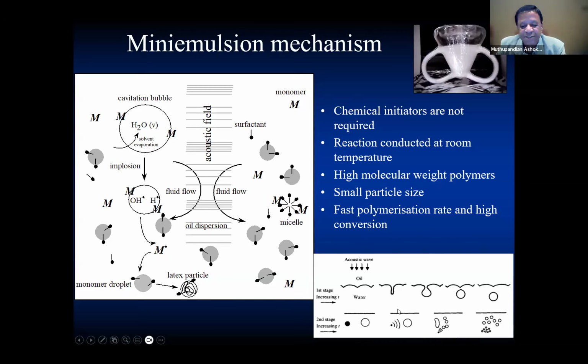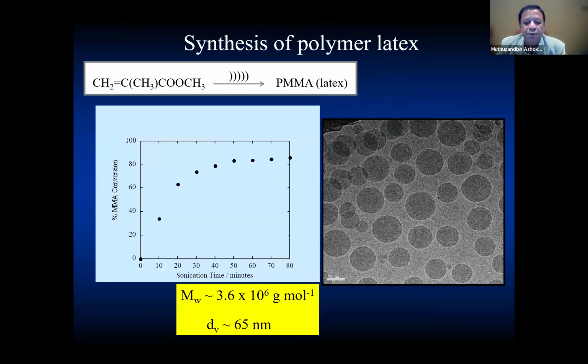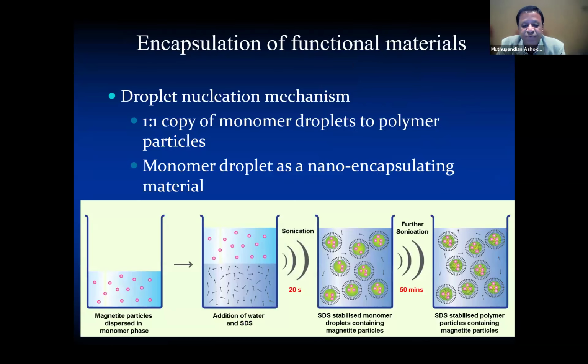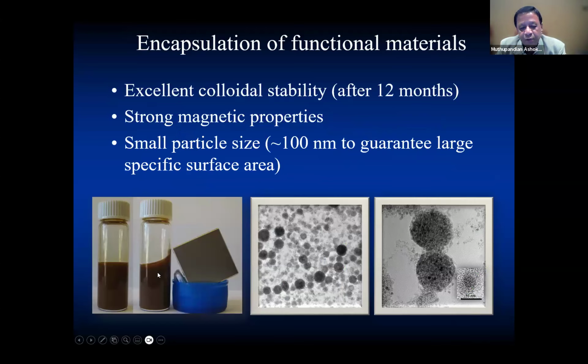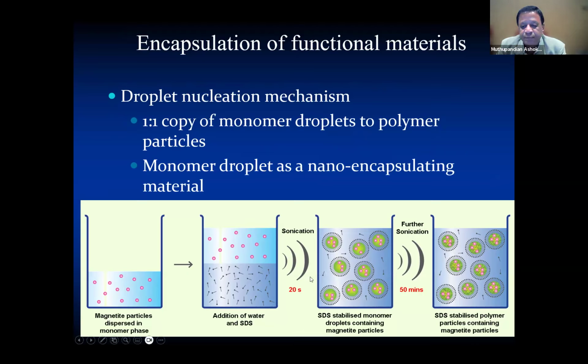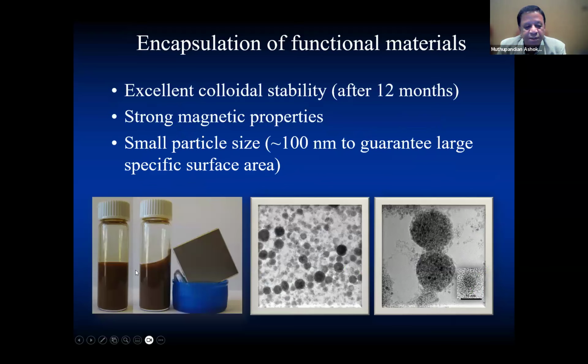Again, there's a specific mechanism involved in terms of how the ultrasound is generating the emulsion droplets. I'll try to skip that because I think I only have another 10 minutes or so to go through some examples. So using this process, for example, I can make magnetic nanoparticles. In this case, I use magnetite iron oxide particles and put them into the monomer. When the monomer droplets are generated, the iron oxide particles are also part of the monomer droplets. So when I convert the monomer droplet, the iron oxide particles are embedded within the polymer or latex particles, and the whole solution becomes magnetically active.